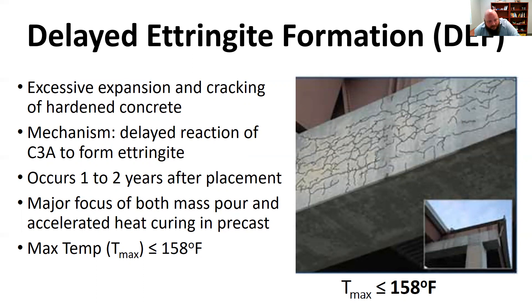The C3A reaction will actually delay — so maybe a year or two years later, that C3A starts reacting again. It can cause excess expansion and cracking because the hydration products the C3A is producing, largely ettringite, will start cracking because there's no room for the ettringite to go.